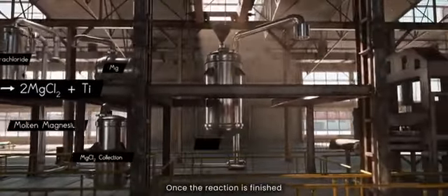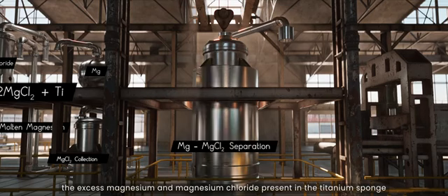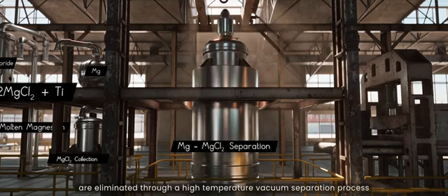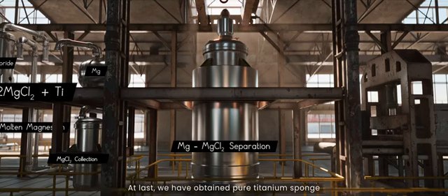Once the reaction is finished, the excess magnesium and magnesium chloride present in the titanium sponge are eliminated through a high-temperature vacuum separation process. At last, we have obtained pure titanium sponge that is in the form of porous granules.